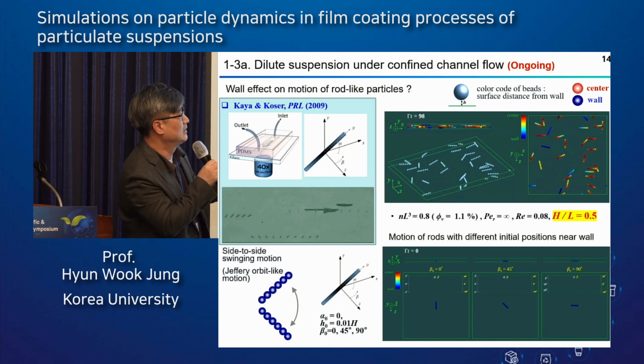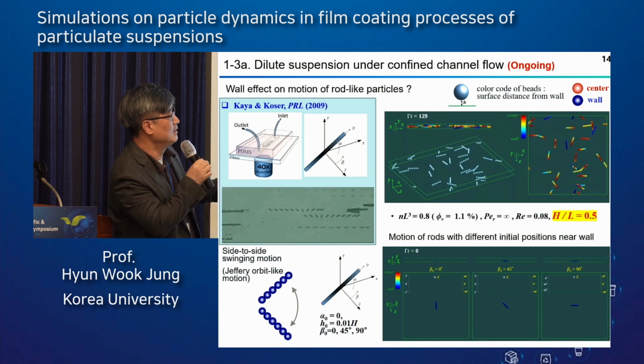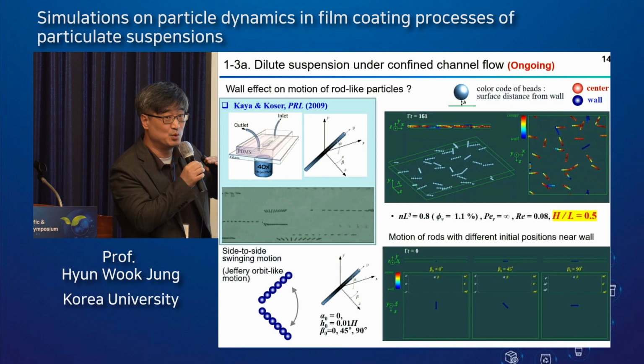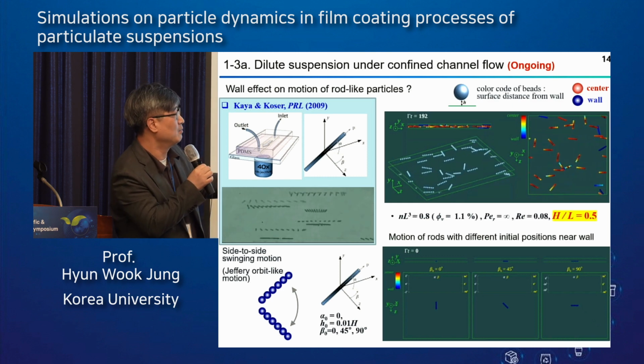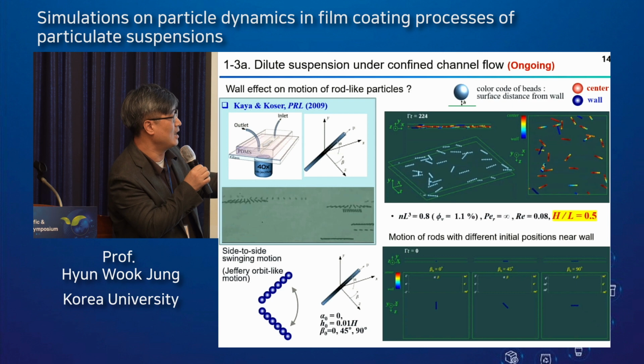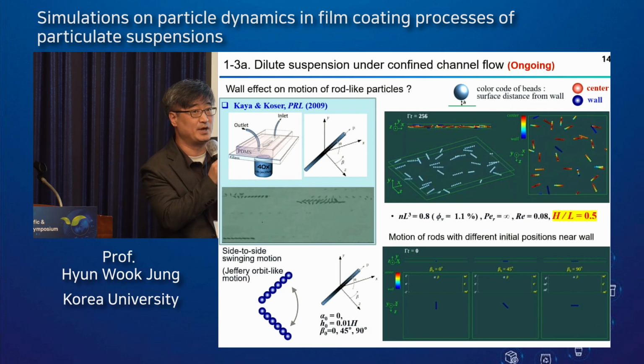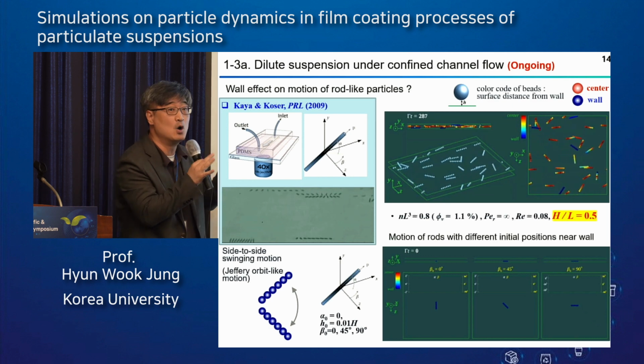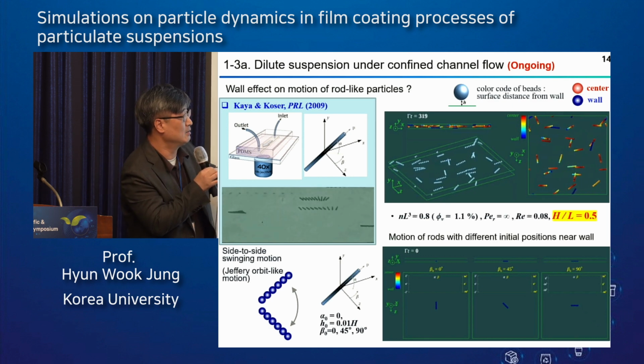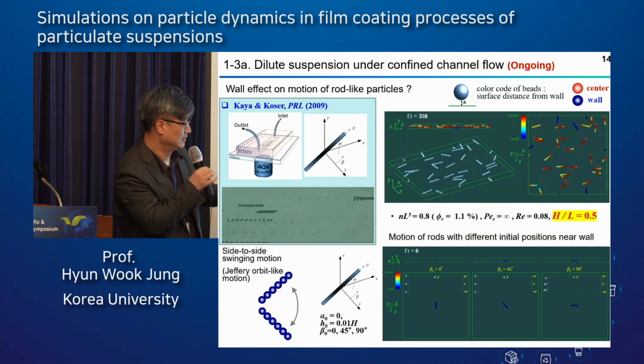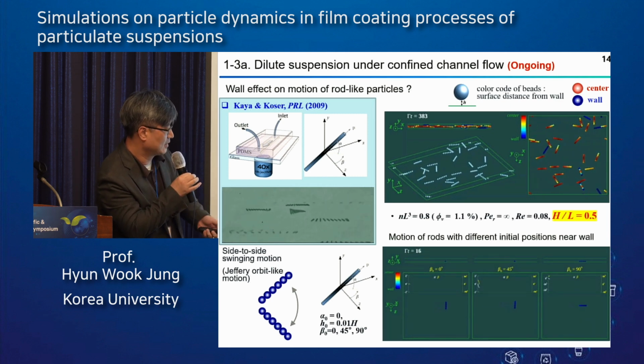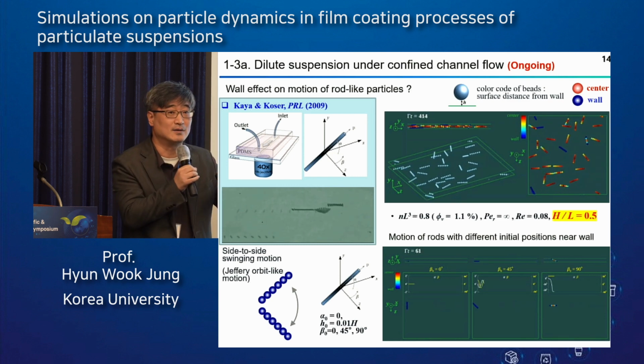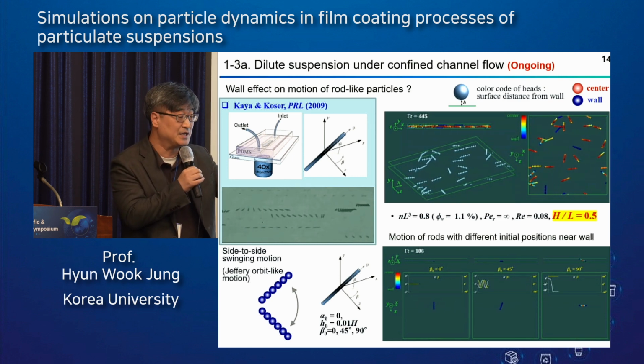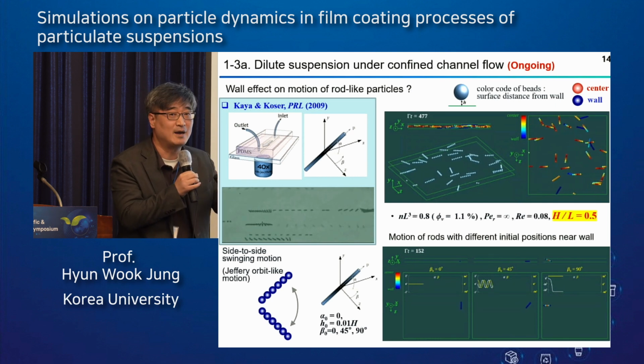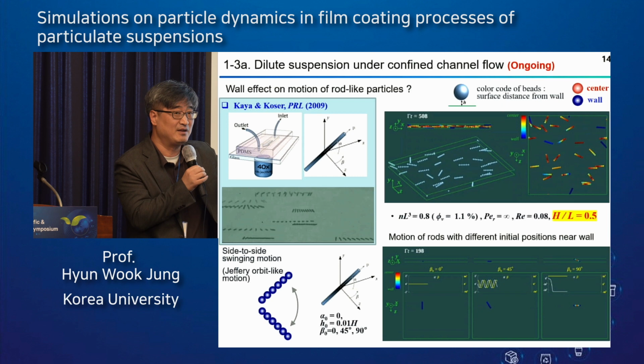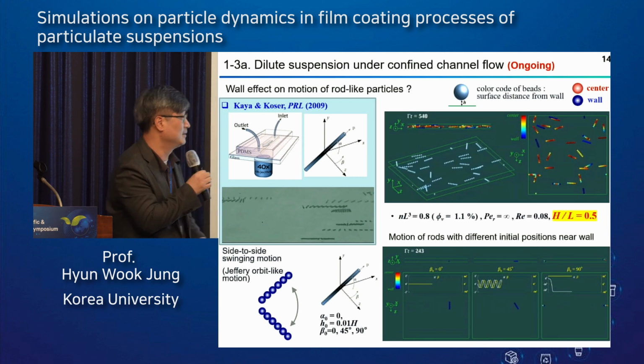You can see some moving colloidal rods, but in different colors. All the blue colored particles are moving near the wall, and the other colloidal rods are moving in the mid-plane region. So let me focus on the blue colored ones moving near the wall, as shown here. Okay, so we found that the colloidal rods are periodically swinging near the wall, if the particle is initially somewhat tilted up and down near the wall, as shown here.